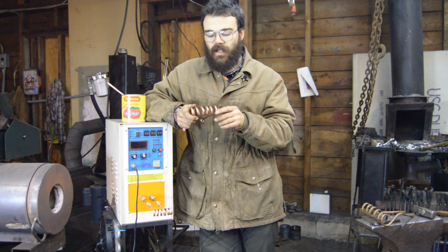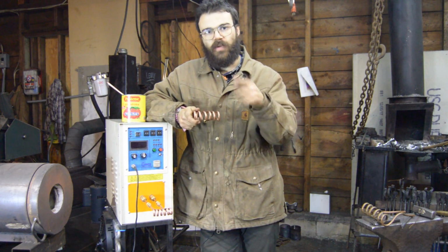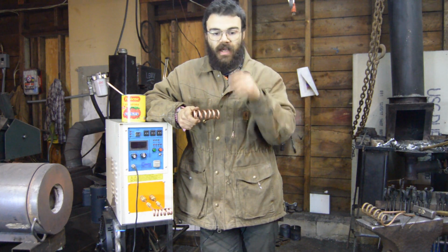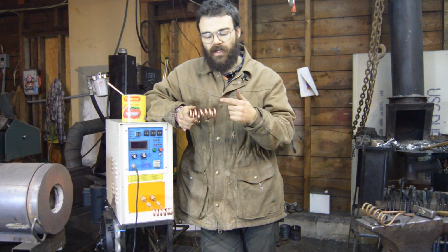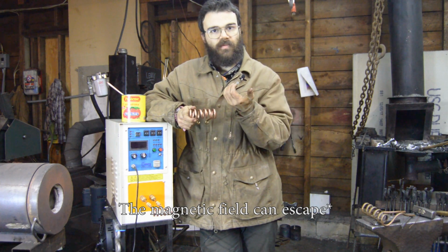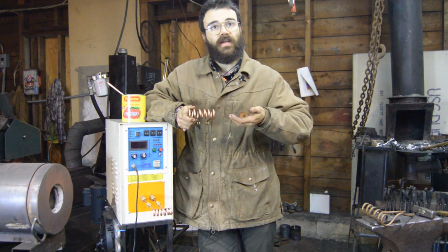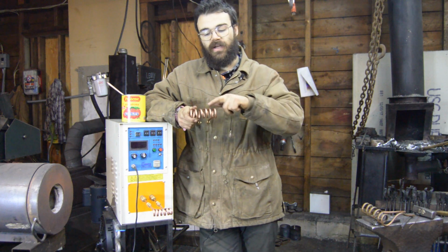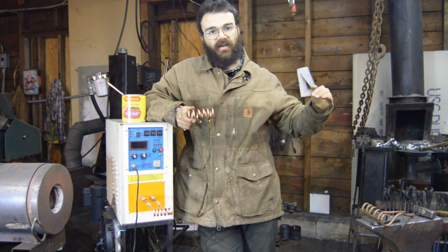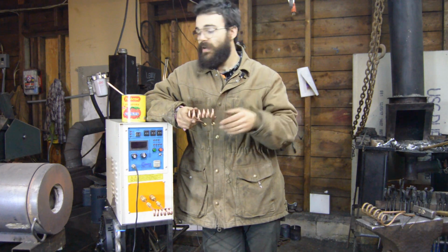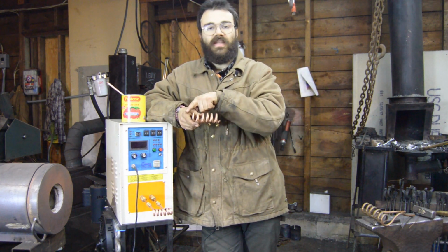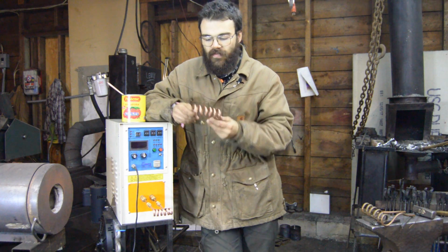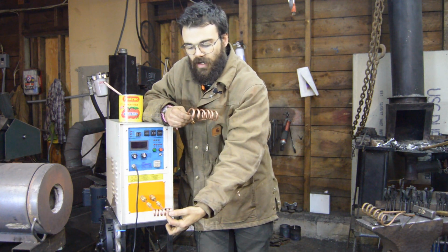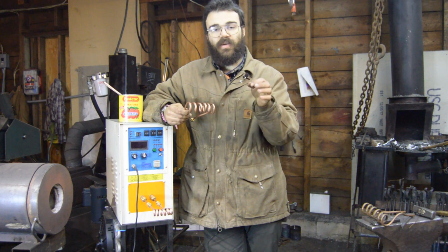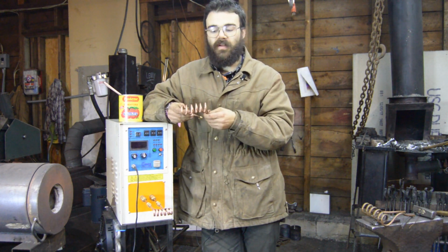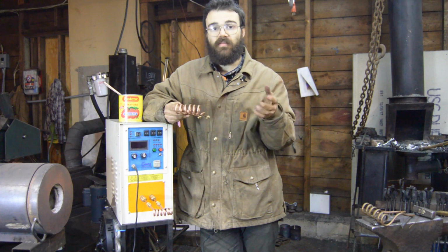Another thing that's important is that you want to keep the spacing between each loop in the coil very tight, or as tight as possible. The reason is that as current is going through here, it can have the chance to escape, right? Because the magnetic field lines are wrapping around the conductor. If there is another conductor loop nearby, those magnetic field lines will continue through the coil. But if it's not, they'll just start wrapping around the coil as if they were at the end of the coil. They don't know. So if you keep the coils with a gap of about half of the tubing diameter, that's the best possible. You'll have very little leakage of the magnetic field lines, and you'll have more efficient heating.